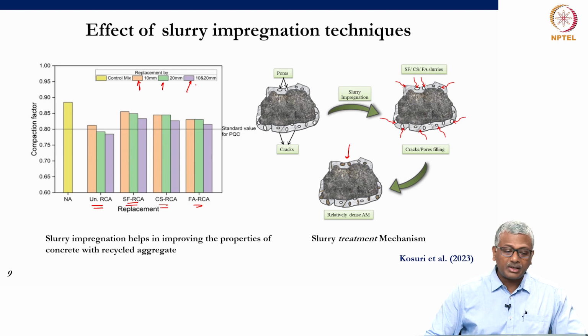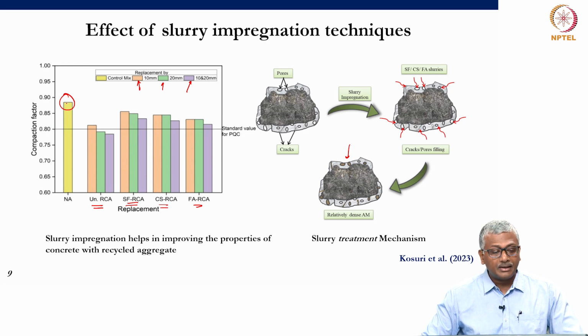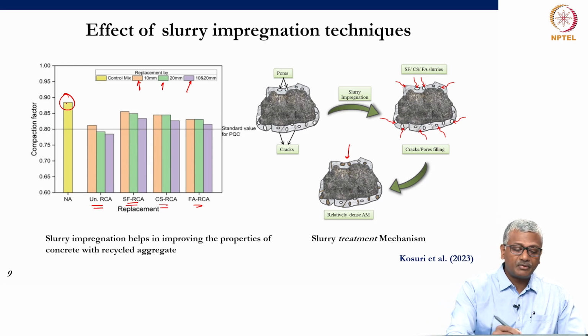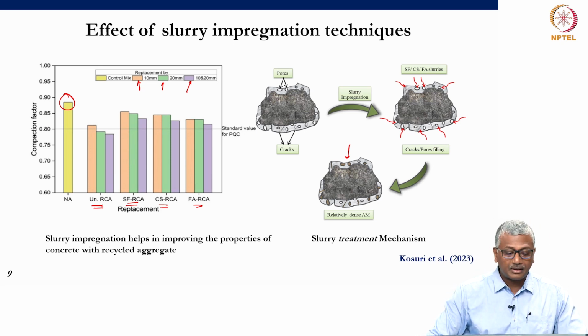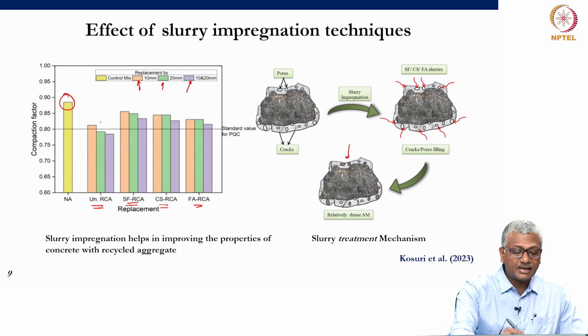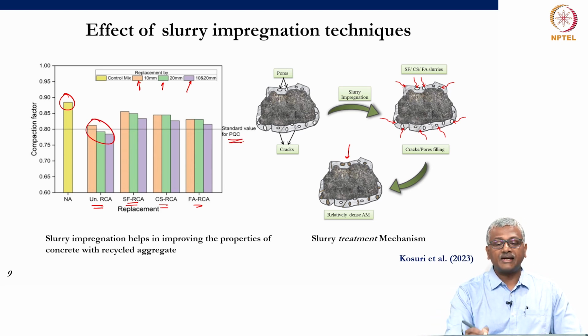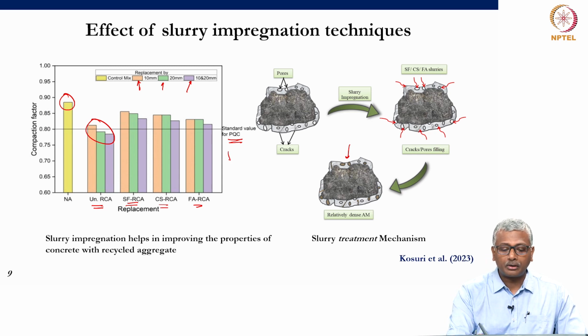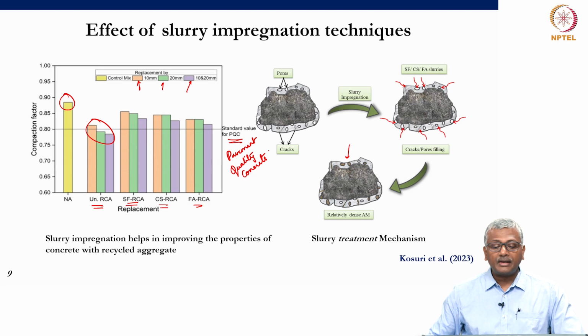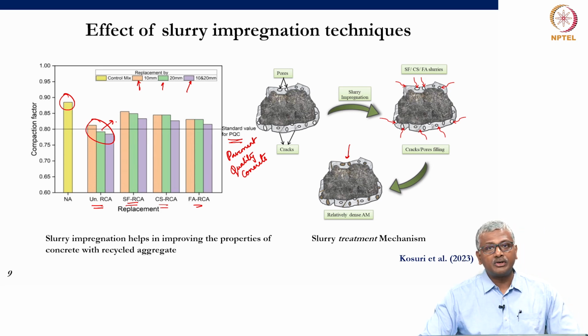So, in this case, what you clearly see is the compaction factor achieved from the concrete with the natural or normal aggregate is close to 0.9, whereas when we do with the untreated recycled concrete aggregate, untreated without any treatment, you are getting less than 0.8. Now, 0.8 is the standard value that is required for pavement quality concrete. This is an application that was attempted for pavement quality concrete. That is why that particular limit has been shown here. And what we could see is that because of slurry impregnation, the compaction factor could now be enhanced, right. We could take it to a level much beyond 0.8 and make the aggregate suitable for use in pavement construction.